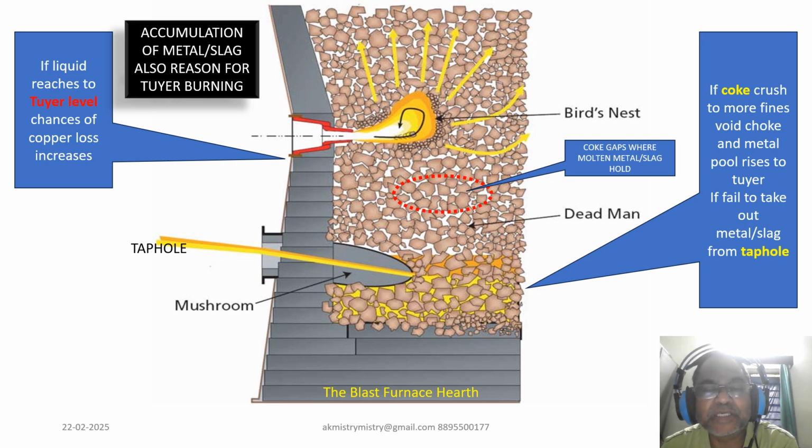You must keep on monitoring the coke parameters on a day to day, shift to shift basis, and see also what the bottom differentials are. And of course we can see those DCI values or the alkali load, because even though our coke texture is good, if alkali load is there in the bottom, or we can say if alkali retention is there, then coke fragmentation occurs, and the coke will automatically lose its texture due to this alkali influence.